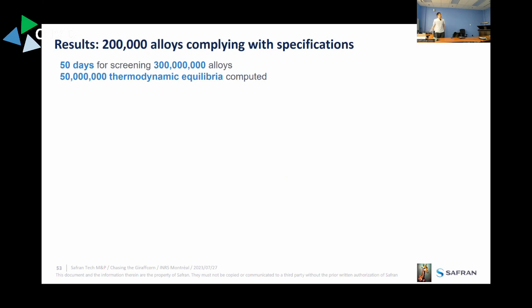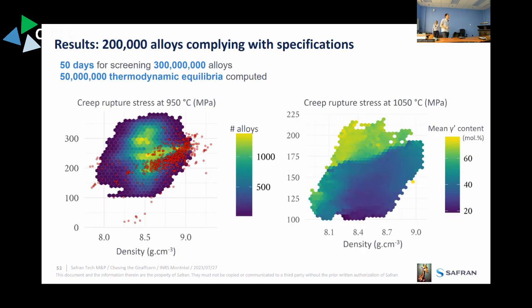And so we screened all these alloys. And that's what I love this morning, because CALPHAD calculations are long. You know, it's 200 milliseconds. It's long, for us it's long. So it took 50 days for approximately 50 million thermodynamic calculations, because you apply a strategy where you do the cheapest calculation first and then the costlier ones later. And you have some results there. On each criterion, we put specification values to attain. And we had about 200,000 alloys that complied with the specification.